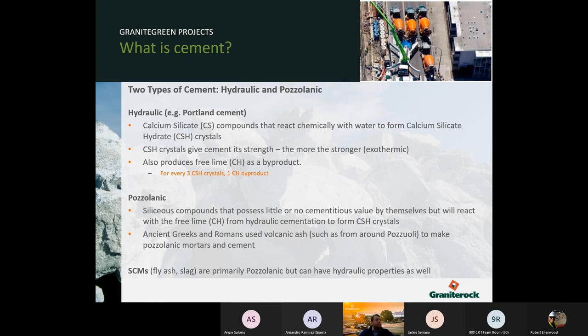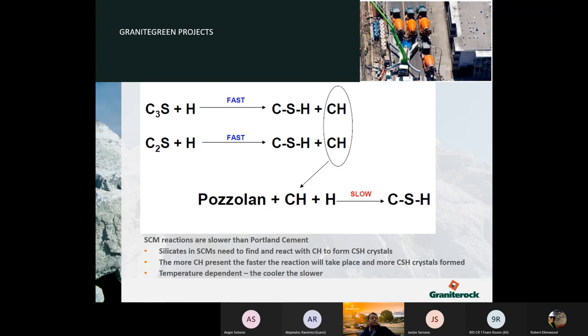It also produces free lime, CH, which is the byproduct that I've been talking about. Pozzolanic is a siliceous compound that possesses little to no cementitious value, but reacts with the free lime, which is the byproduct, to create more of the calcium silicate hydrate crystals. Like we talked about, fly ash and slag are primarily used in our market. Here's a visual of the reaction to give you kind of an idea.